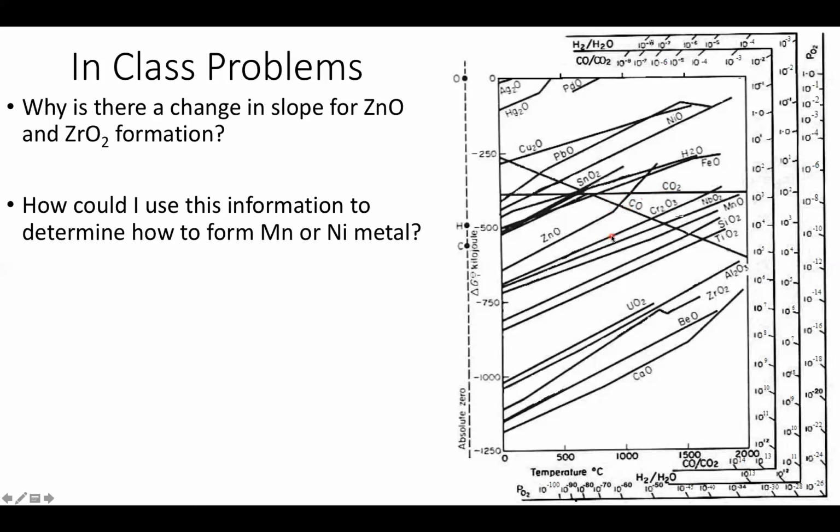So if I get to a high enough temperature, say about 1200 or 1300 degrees, I can reach this critical point at which mixing manganese oxide with coal will preferentially produce carbon monoxide and pure manganese metal. So essentially any point after this crossover. So this gives us a good way of forming manganese metal through simple application of heat and the correct starting materials.